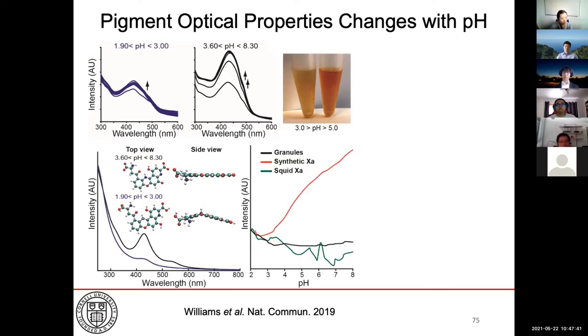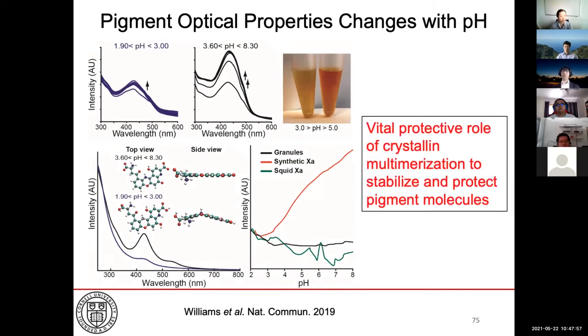And for the final proof of the pudding, the pH is varied for the extracted pigment molecules and the granules, and now we no longer see any transition in the absorption spectra because both of these are rich in crystallin. Now we verify the vital protective role of crystallin multimerization to stabilize and protect the pigment molecules.